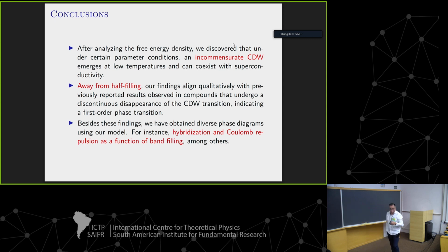Let me show my conclusion. After analysis of the free energy, we discovered that under certain parameter conditions an incommensurate charge density wave emerges at low temperatures and can coexist with superconductivity. Also, away from half filling, our finding aligns qualitatively with previously reported results observed in compounds that undergo a discontinuous disappearance of the charge density wave transition, indicating a first-order phase transition.